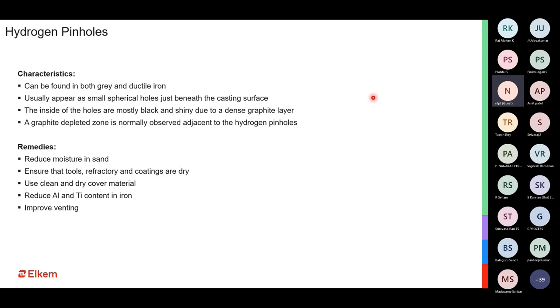We also have to see how we reduce the aluminium and titanium content, because in the presence of high aluminium, hydrogen pinhole tendency becomes more. And of course, when you have gas, you have to make sufficient provision to ensure that the gas escapes and does not get trapped within the cavity of the mold.